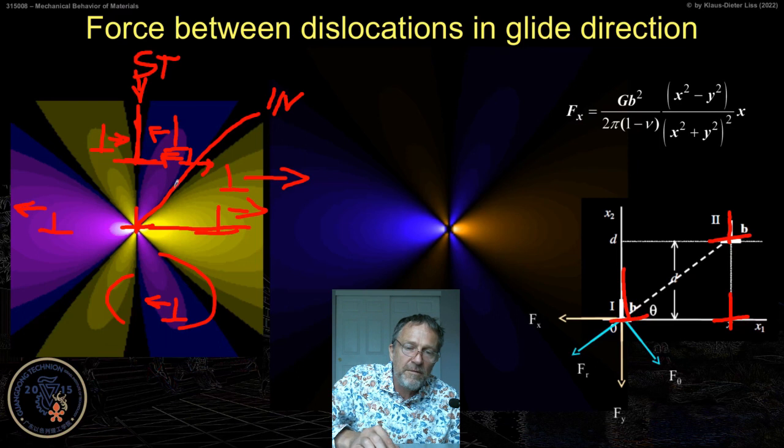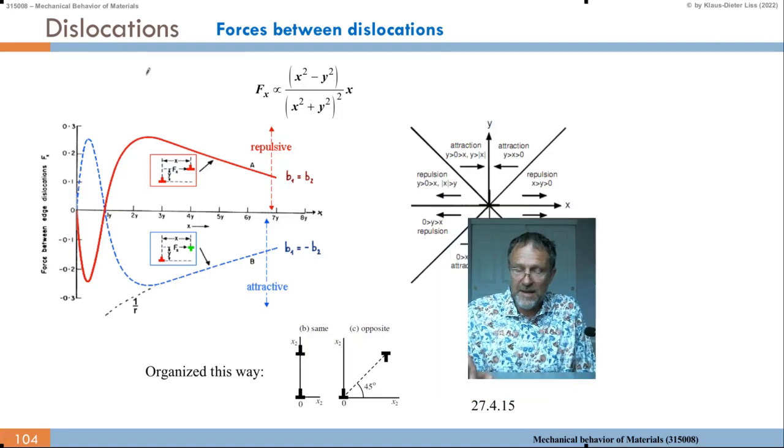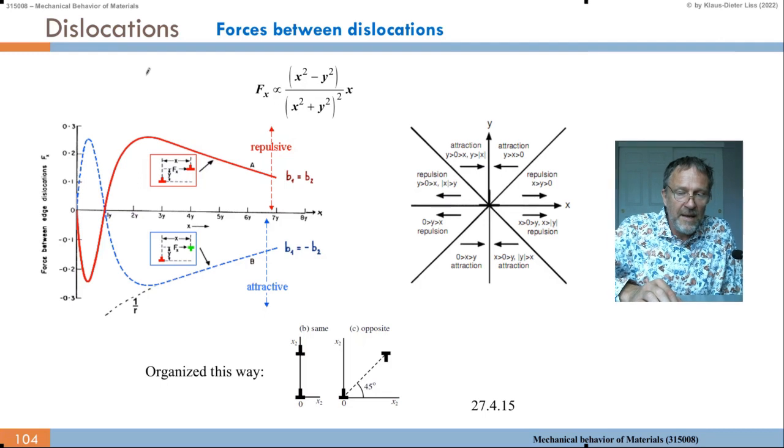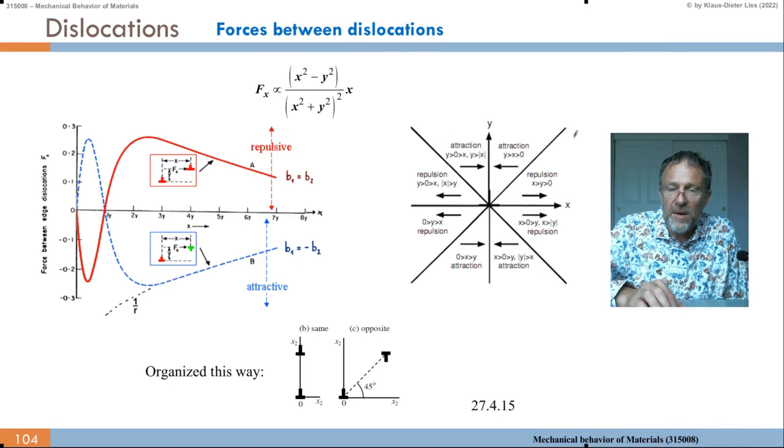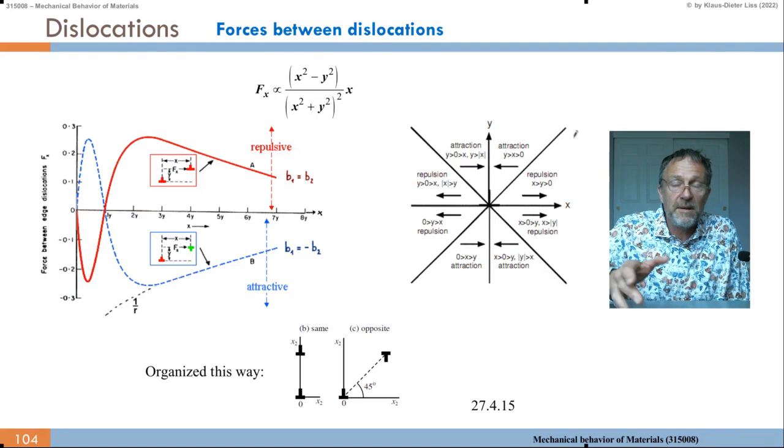So I may have dislocations here at 45 degrees, which are born somehow there, but eventually when they overcome the yield stresses, they move towards this stable line of arrangements. And that gives me dislocation arrangements. It's also shown here in those diagrams. So here we see again what I showed on the colorful figure just before. You can put it in MATLAB and plot it.